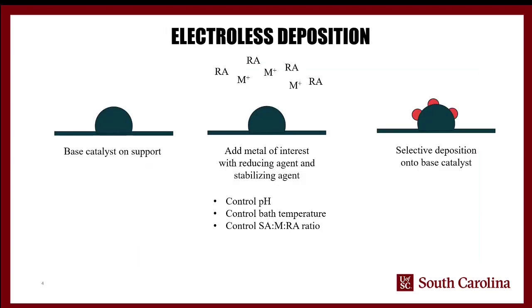So let's talk about the way that we're going to actually make this catalyst. There's a couple of different ways that you can try and make bimetallic particles. You can just do a solution-based approach, metal salts in a liquid. You add a reducing agent. Both of the metals get reduced, generally at the same time, and you kind of hope that the two reduce together onto the same substrate. That works to an extent, but what happens in practice is that you end up with a few bimetallic particles, but you also end up with monometallic particles spread all over as well.